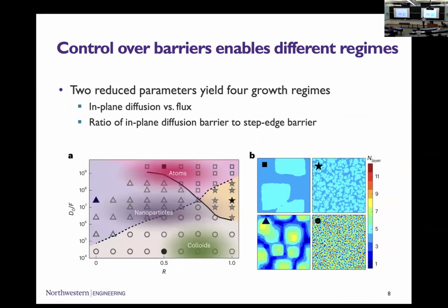And so doing the matching simulations, we realized, well, it really depends on how fast particles are raining down compared to the rate at which they are moving on the substrate. And theoretically, it's easy to see that there should be quite a few different regimes, in fact, 4 different regimes. And if you go into the literature, you realize that some of these have been seen a lot, others have barely been seen. They're like occasional reports. In this nanoparticle system, because we can tune the particle's shape, we can change the interactions, we can actually realize all these regimes.